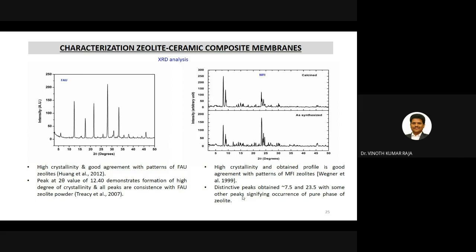The peak obtained at 2 theta value of 12.4 demonstrates the formation of a high degree of crystallinity, and all peaks are consistent with the FAU report.